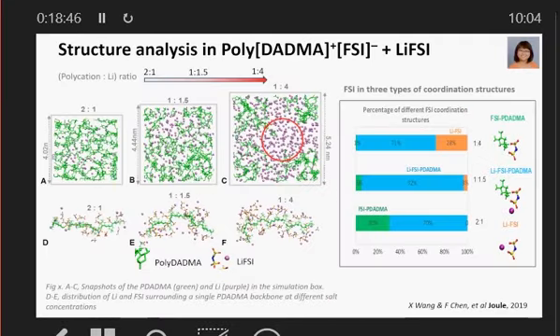What she found in these systems is there were always three different types of coordination environments predominant. There was the polymer FSI, or TFSI or whatever the anion is that you have, and that polymer-anion-polymer interaction is what controls the Tg of that polymer. It's almost like a virtual cross-link. So that is a very important interaction, which is broken down as you add more lithium salt, because now what you end up having is a lot more polymer-FSI-lithium